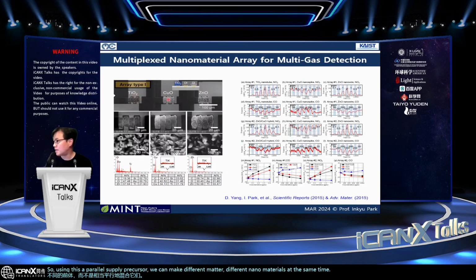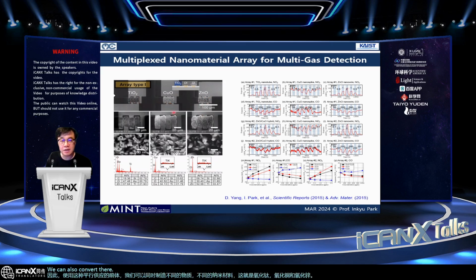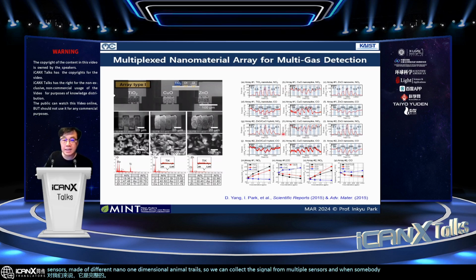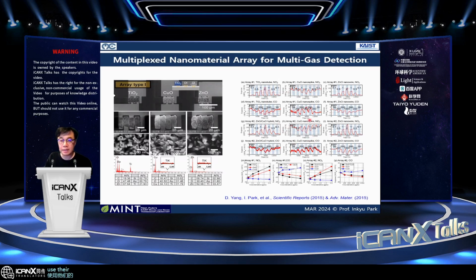So this is the titanium oxide, copper oxide, or zinc oxide. We can also convert their surface with additional coating with the metallic nanoparticle precursors too. So after making this, this is an image of one device. From here to here is only about 400 micrometer across. It's integrated sensors made of different one-dimensional nanomaterials. So we can collect the signal from multiple sensors, and when some gas is given, we can use their response to analyze which gas it is.